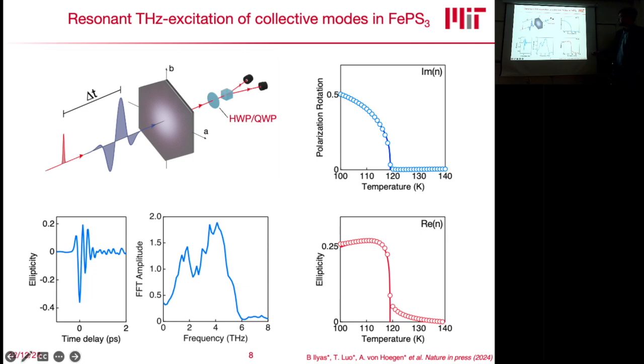And so this is a measurement down here. This is our terahertz pulse on a time scale of time delay, and we measure the ellipticity, again similar to before. And if you take a Fourier transform of this, you get this spectrum over here. This is our excitation spectrum. And if we now draw in the lines from these Raman measurements, we can actually find very good overlap between the phonons and our excitation spectrum. There's only one phonon mode that's outside our excitation spectrum. And we actually find that also the magnon is covered by our excitation spectrum. So we are able to excite these modes using our terahertz light.